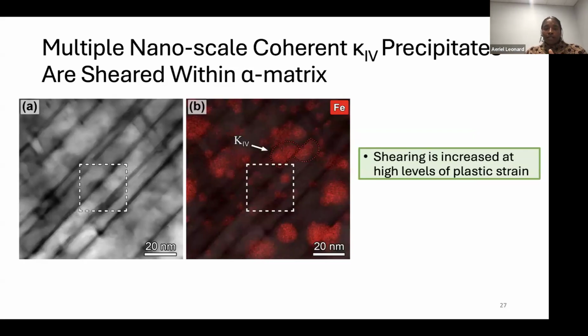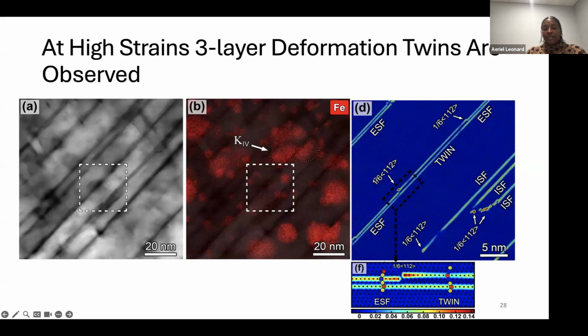As we look closer at these higher levels of strain, what we can see is that we have a lot of sheared Kappa 4 particles. Kappa 4 is iron-based, so you can see that there are a lot of sheared particles. This is a very nice one here. If we take a closer look, we can see that within these regions, we have extrinsic stacking faults and intrinsic stacking faults, as we saw earlier, but something that we did not have before are deformation twins, right? At these high levels of strain, we're reaching the stress levels needed to form deformation twins in our material. Stacking faults and twins are very important because they also help facilitate hardening behavior in the material. So again, really understanding what is driving the strength in the material, but then also, because we have a lot of easy paths for dislocation motion, also helping facilitate an increase in ductility in the material as well.